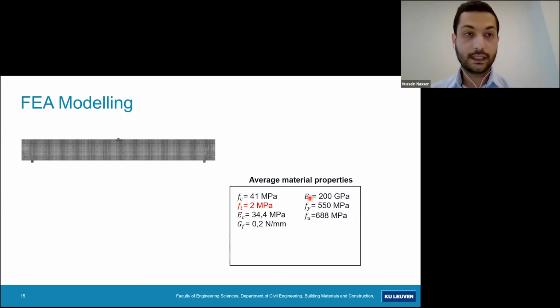The model was built in Diana using 2D plane stress elements. The average material property related to the compressive strength was used, which was calculated from tests on cubes, while the characteristic uniaxial tensile strength was used. I used grade 500 steel, so I used the average values of that type of steel.